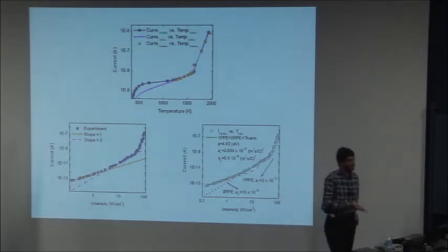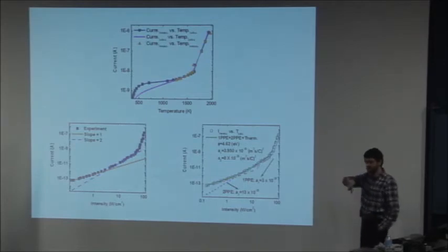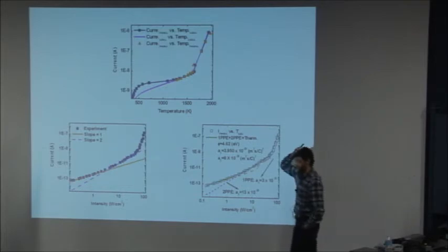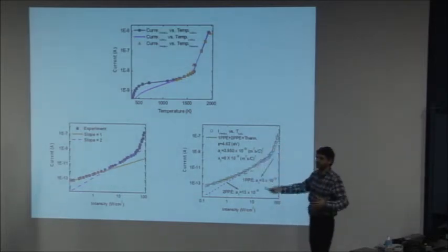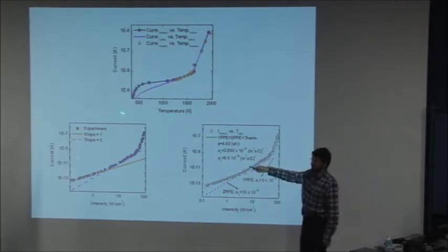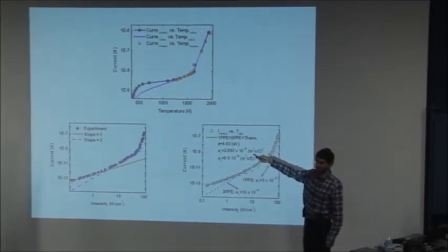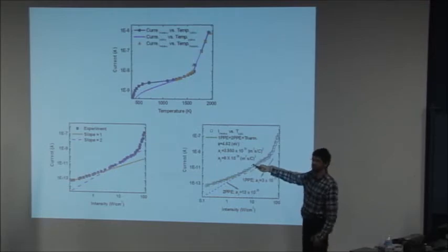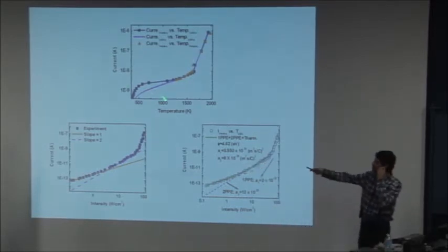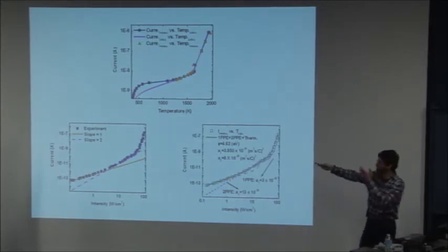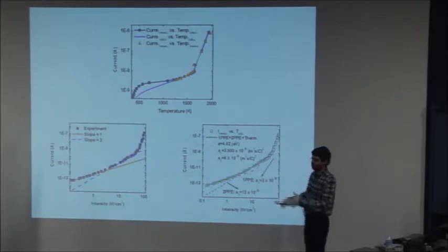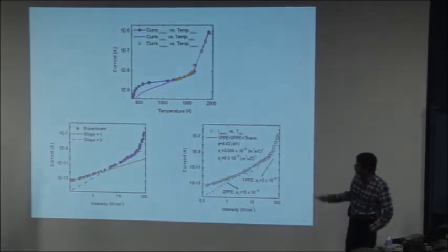And as recently as last year or 2 years ago, you would see the same sort of artist's impression or theoretical version of this curve in papers showing the combined effects of light and heat on electron emission. What I'm showing you here is an experimental example of that, which is happening because you can do this very easy heating with a low-power ultraviolet light, which you don't easily find in the literature, the experimental version of this. So it's very interesting to people who do photoelectron emission like myself.